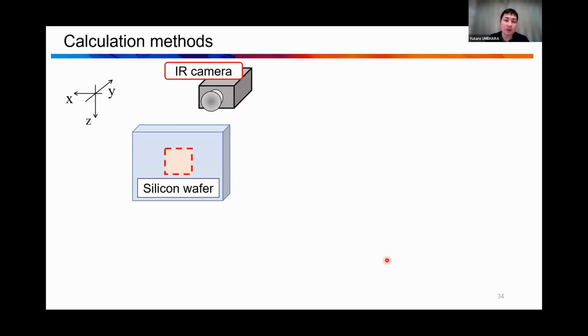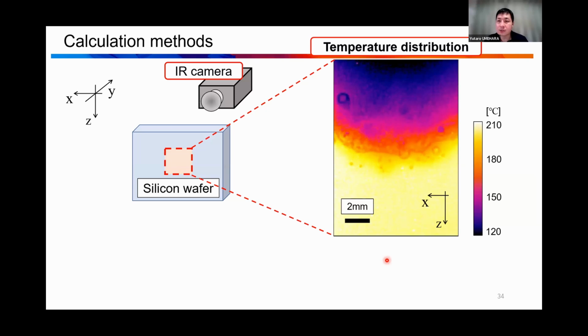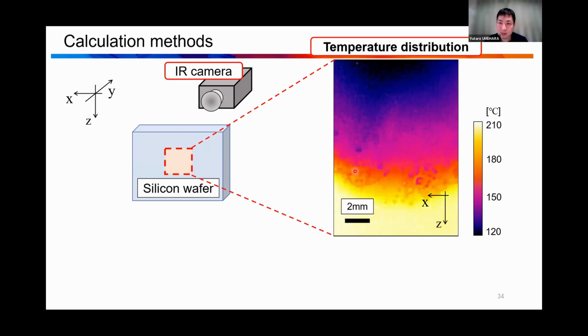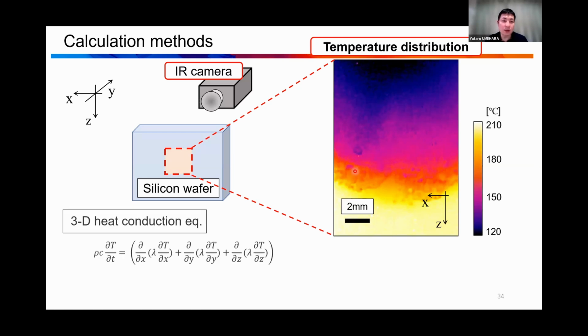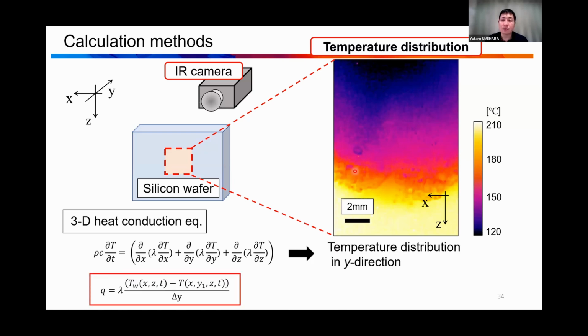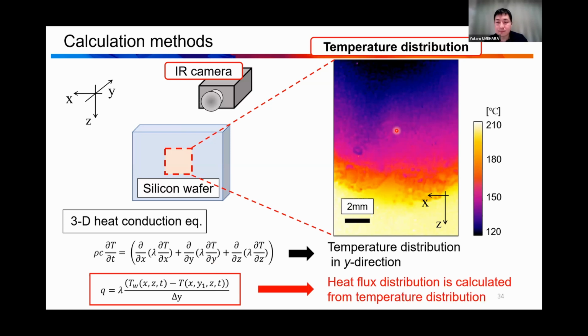We got the infrared camera image like this. It is the actual temperature distribution like this during the falling film from the top. And then based on this temperature distribution, we calculate a three-dimensional heat conduction equation. And then we got the temperature distribution in the y direction. The y direction is the thickness direction. Okay. So based on this temperature distribution in the thickness, in the y direction, finally we got the heat flux on the surface. Also, we can get the surface temperature from this.